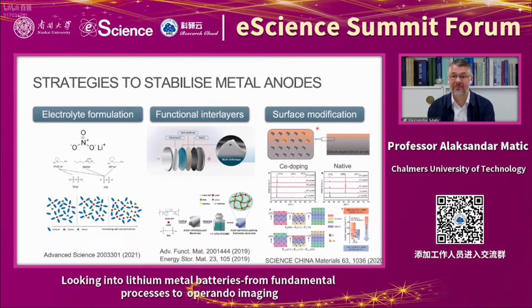The most advanced is, of course, that you could engineer the lithium itself. Here is an example of the work of Shizhao Xiong, where he and colleagues used cerium doping to modify the surface of the lithium anode and promote the growth of certain crystalline directions which do not form dendrites in the end. Of course, this is super elegant, but also very difficult to do on a large scale. And the most simple is, of course, to just modify the electrolyte formulation.